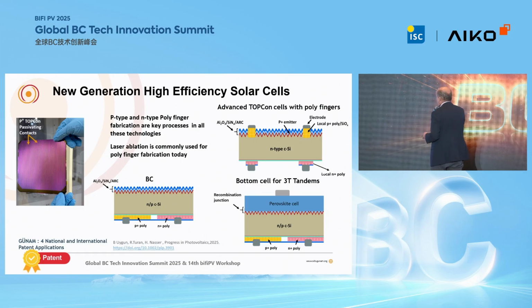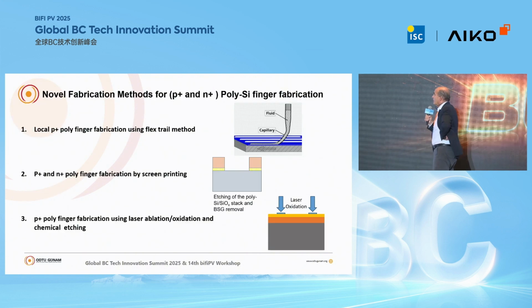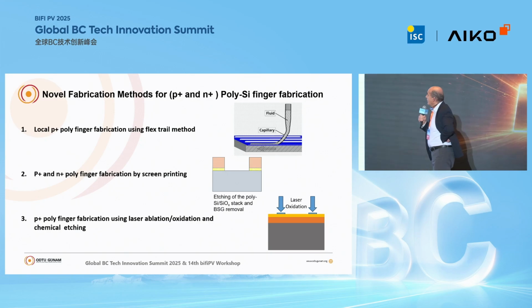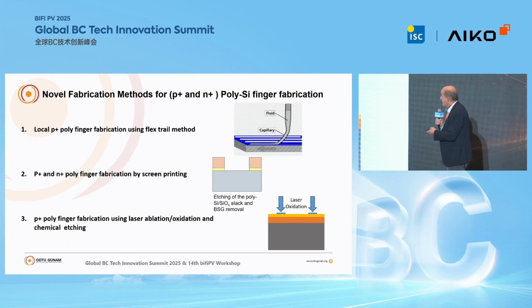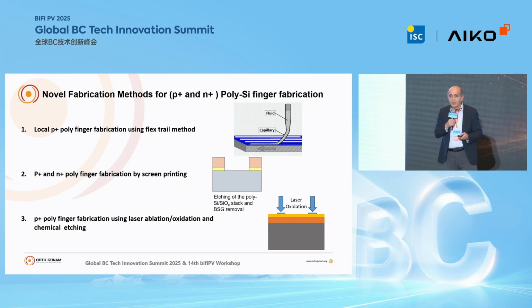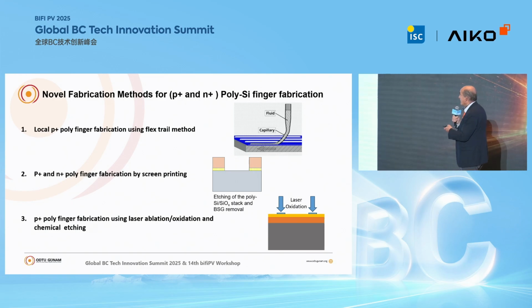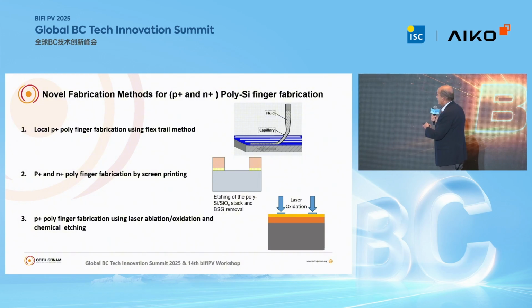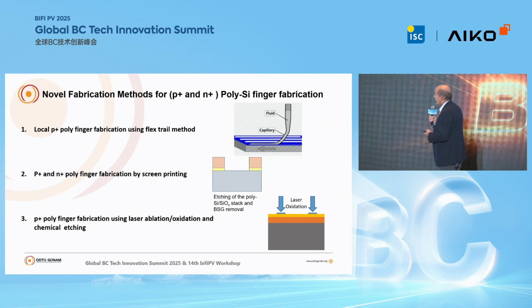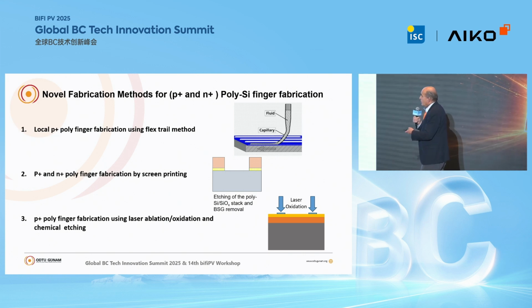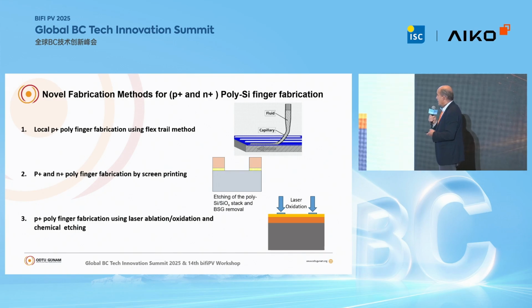including ISC. Well, okay, I would like to present some alternatives today. One of them is based on printing, actually. This is a kind of inkjet printing, but they call it flex trail. This is developed by Fraunhofer ISE. And we use this technique to print boron ink on the polysilicon and selectively etch the polysilicon to fabricate polyfingers. And also screen printing can be used for the same purpose, and laser oxidation is also well known today.